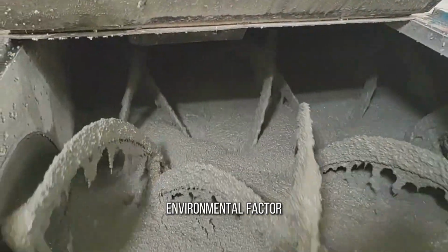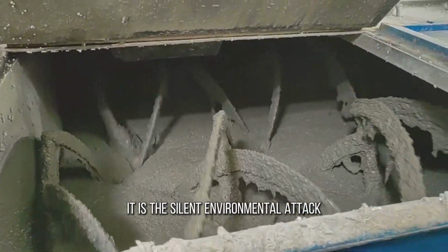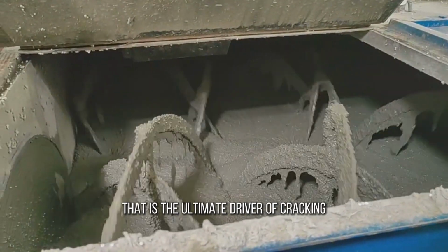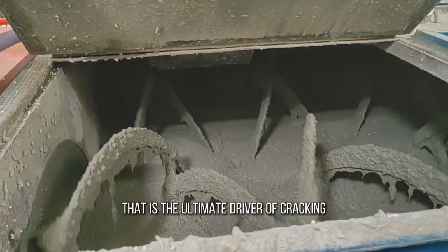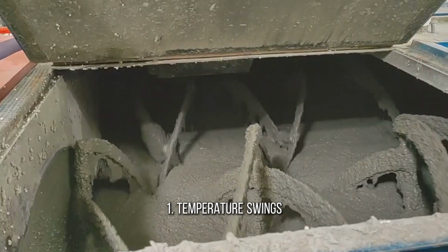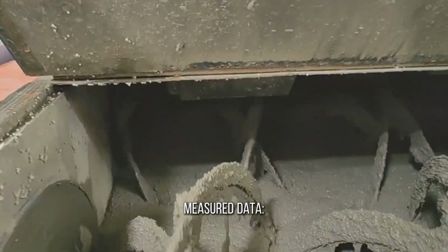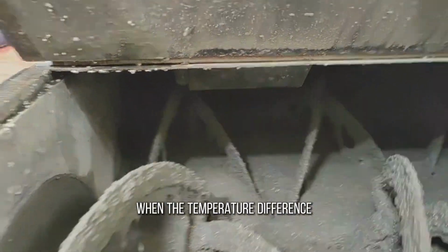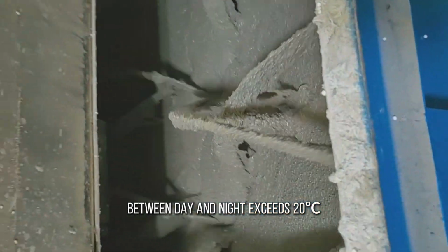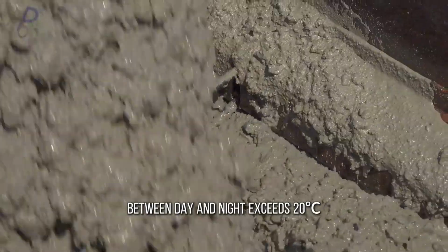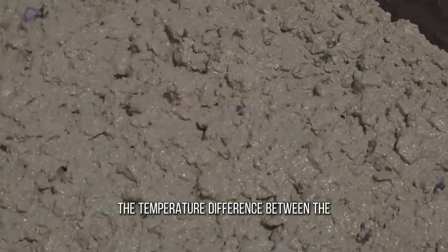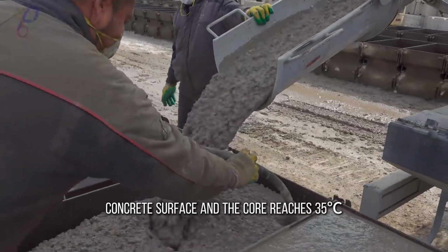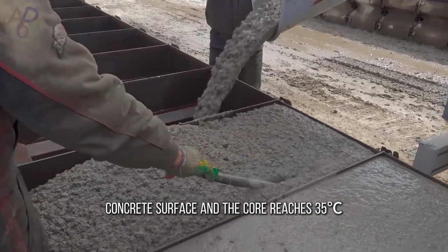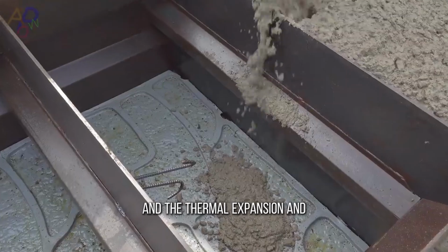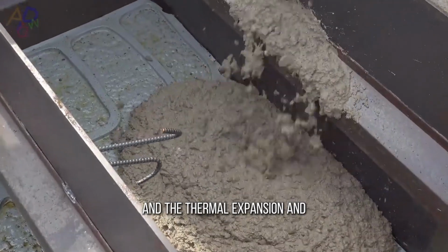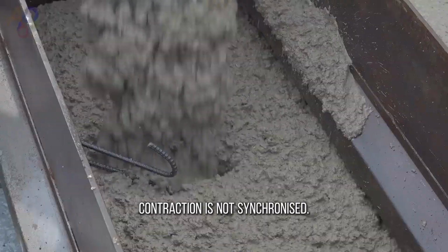Environmental factor. It is the silent environmental attack that is the ultimate driver of cracking. One, temperature swings. Measured data: when the temperature difference between day and night exceeds 20 degrees Celsius, the temperature difference between the concrete surface and the core reaches 35 degrees Celsius, and the thermal expansion and contraction is not synchronized.